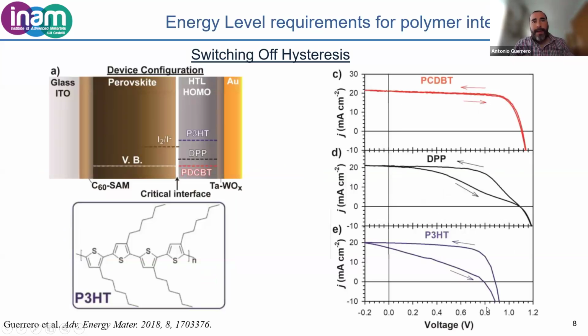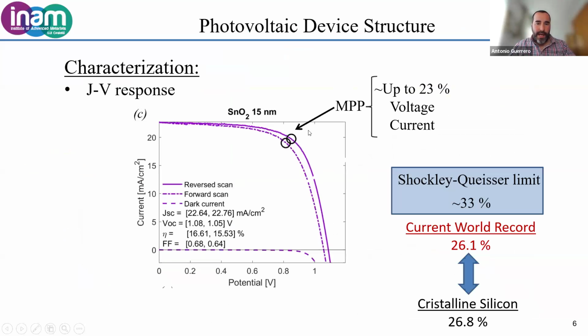Because I'm going to speak about memory devices, it's very important to discuss the hysteresis that is observed during the IV characterization of the device. There's one feature which is quite important for this type of materials: when we apply this potential and we do the sweep of the potential and we measure the current, we don't get the same values of currents when we go forward, from 0 to positive values, than when we go backwards, from open circuit conditions to 0. And these lines don't overlay on top of each other. This is called hysteresis in the IV curve. And this has been observed from the early times of the development of this technology.